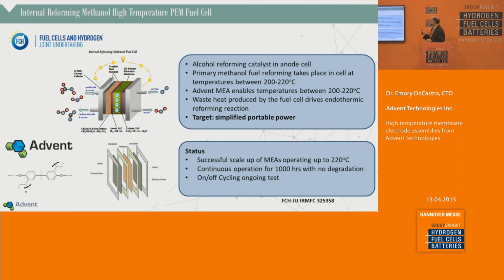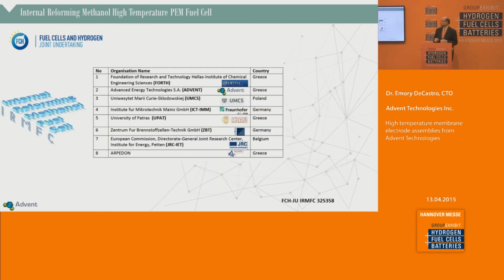And so what this would do then is give us a more simplified portable power system, essentially in situ reforming right within the MEA confines. This program is ongoing, and certainly within our group, we have a successful scale-up of the MEAs operating at 220. We've shown continuous operation of the concept to 1,000 hours with no degradation, and we're just starting our on-off cycling tests. Of course, this is a very complex project.